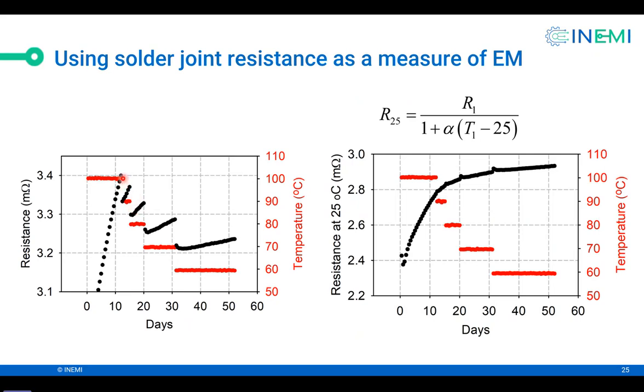So this red line is temperature. Notice the resistance dropped when we decreased the temperature. And then when we held it at 90, it increased. And then we dropped the temperature to 80 degrees. Again, the resistance dropped. And then slowly the resistance increased and so on. Now, notice that these black curves are the resistance, right? So this curve at 90 degrees is approximately a straight line. But at 80 degrees, it starts to have a little dip in the resistance. At 70, the dip is bigger. At 60, the dip is even longer. So the dip lasts for a longer time at lower temperatures.